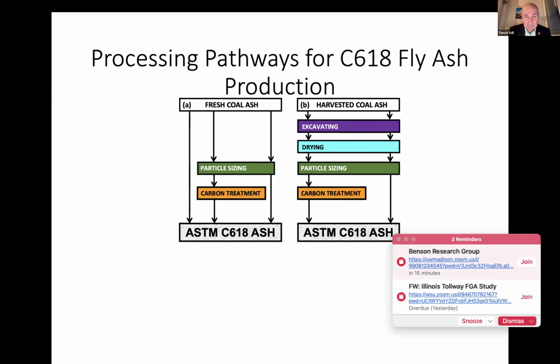On the left, we have fresh coal ash, and on the right, harvested coal ash. And you see fresh coal ash with very little processing, whereas harvested fly ash, you have to excavate it, dry it, and adjust the particle size and carbon treatment, remove the carbon. And this is a little more complicated, but I want to show you all the things involved.